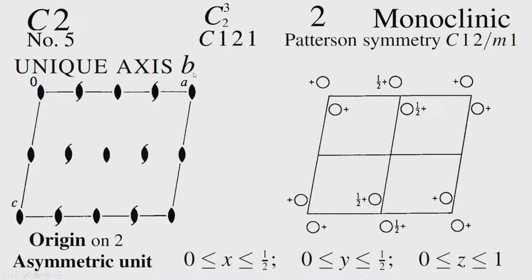Actually, we have been looking at the space group C2 unique axis B, but one issue we have to keep in mind is that the position of the y axis is not unique, the 0 of the y axis. That means the origin can be anywhere along this direction. So, suppose we move the origin to this 2 1 screw axis, what happens?